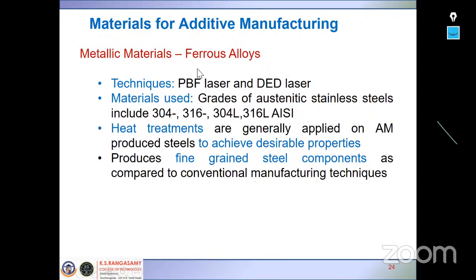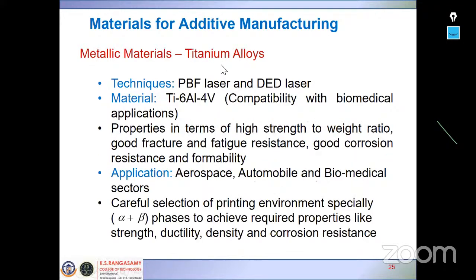One is the ferrous alloys. The techniques used for the ferrous alloys are PBF laser and DED laser, that is, the powder bed fusion method and the direct energy deposition method. The materials used are grades of austenitic stainless steel, including 304, 316, 304L, 316L. Heat treatments are generally applied on additive manufacturing produced steels to achieve the desirable properties, and we can also produce fine-grained steel components as compared to conventional manufacturing techniques.